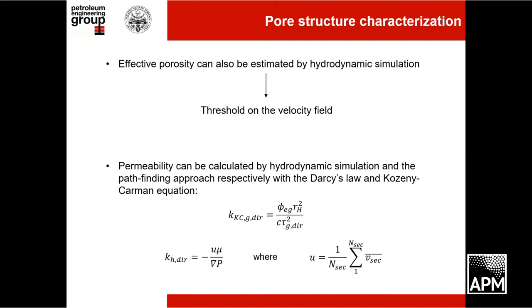Finally, we estimate the permeability. Using the geometrical approach, we take the Kozeny-Carman equation and substitute the porosity with the effective porosity, taking into account only the pore space interested by fluid flow, and use the geometrical tortuosity. We also calculate the permeability from the hydrodynamic simulation directly using Darcy's law, where the velocity is calculated from the lattice Boltzmann simulation.